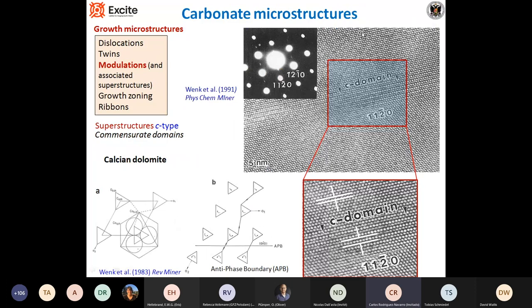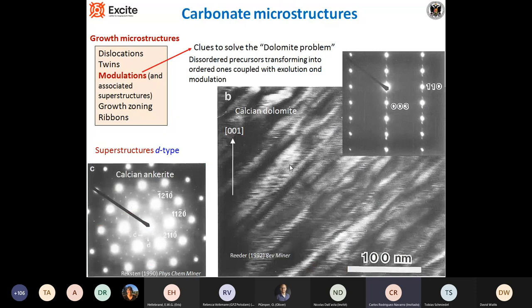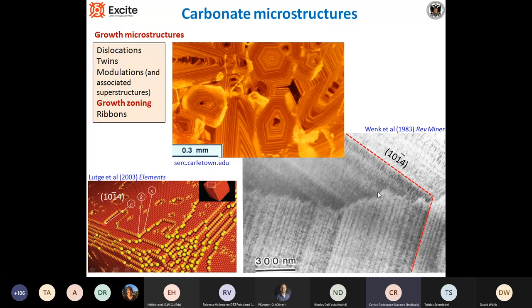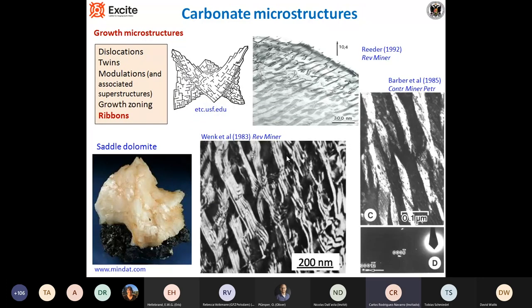C-domains are seen when we have C-type reflections, and may be due — although this is a matter of discussion — to antiphase boundaries, where the carbonate group is oriented in the opposite way across the APB boundary, resulting in doubling of the spacing visible in the TEM. D-type reflections are extra reflections very clearly visible due to the apparent banding — actually a modulation — in dolomite, giving clues about the origin. We can also see growth zoning at the TEM level, with ribbons showing compositional variation in a homogeneous phase, seen very nicely under dark field imaging.